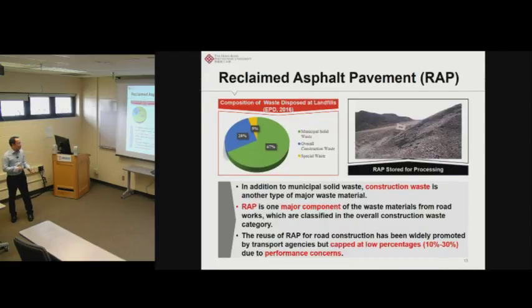This is mainly due to performance concerns, especially the fatigue performance, low temperature cracking performance, and moisture damage resistance, because the aged binder becomes much more brittle. So we have big concerns about cracking resistance and moisture damage resistance. Unless we use certain rejuvenators or some soft binders, we usually control our RAP percentage at a relatively low percentage.